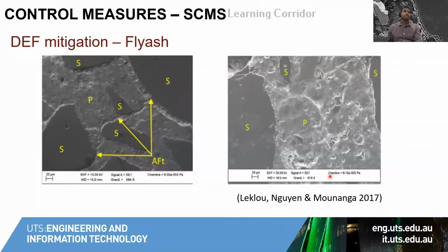Another way is the use of supplementary cementitious materials in concrete. SCMs like fly ash can partially replace cement. First, the sulfates and the aluminates in the system will get diluted because we are partially substituting the cement with fly ash. But it's not only about the sulfate dilution. Here in the example on the left, without fly ash, we can see ettringite precipitating along the aggregate and cement paste interface and causing cracks. Whereas when we partially replace with fly ash, even though it's heat cured, we don't see this precipitation occurring, and there are no major cracks in the system.